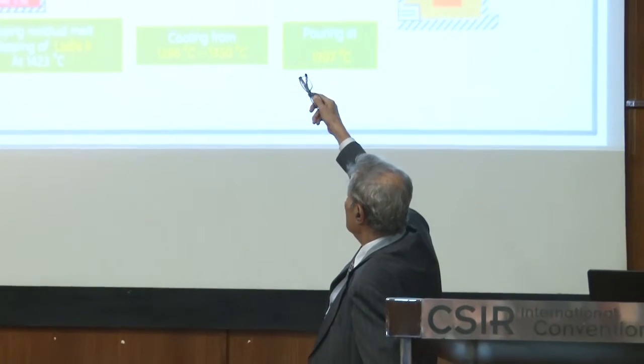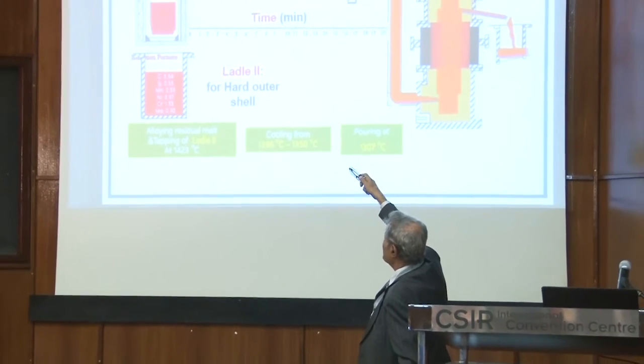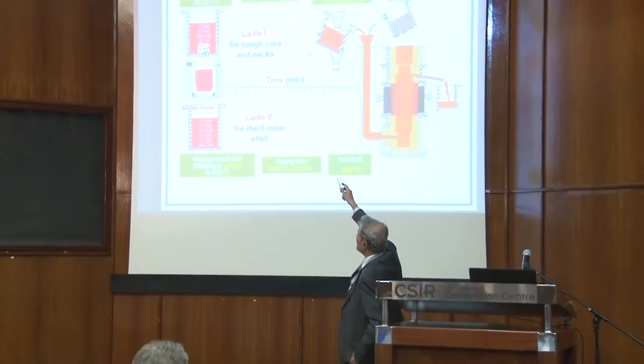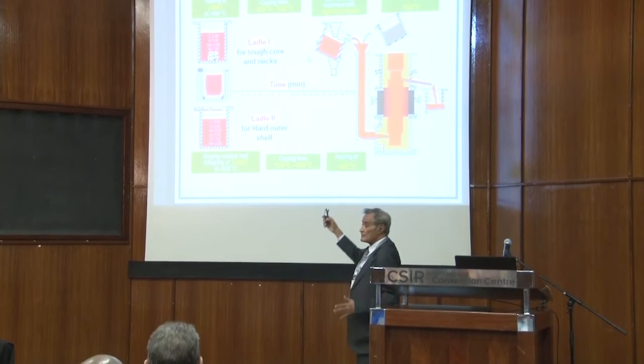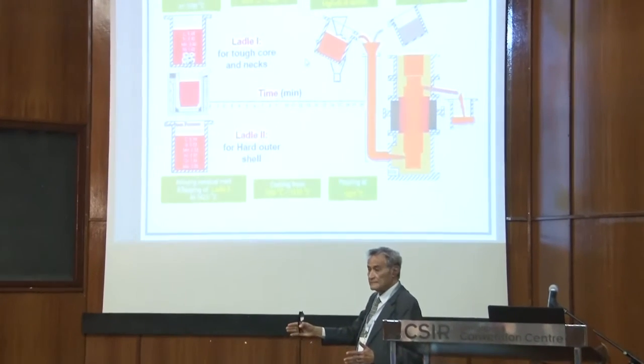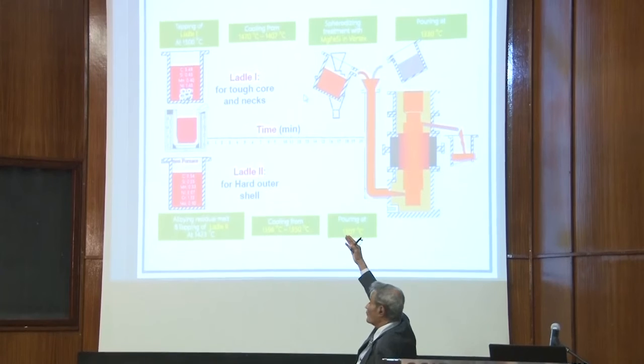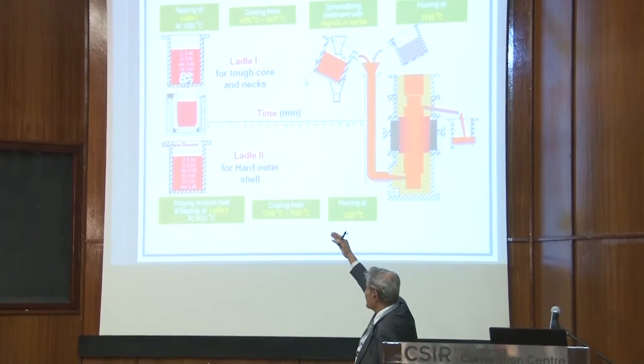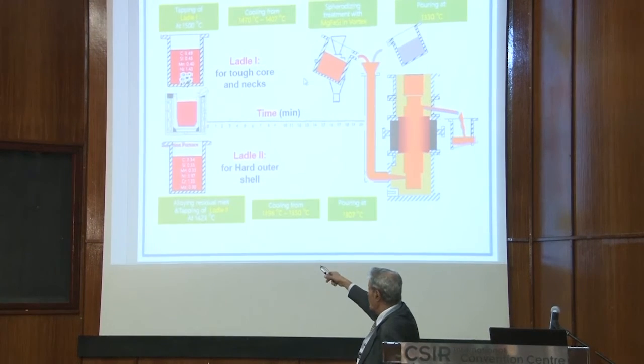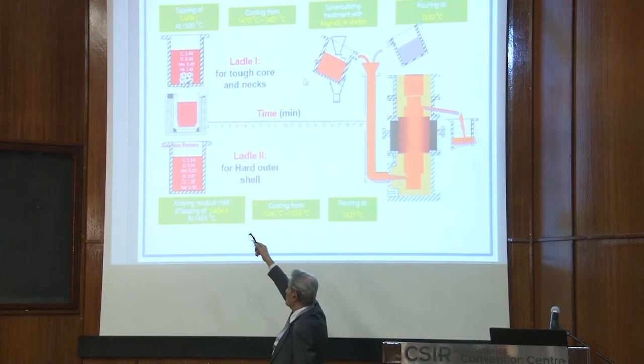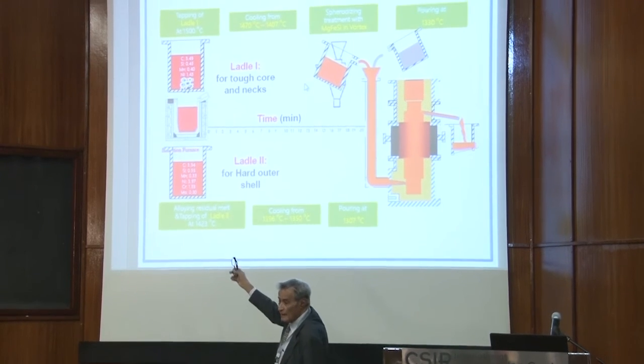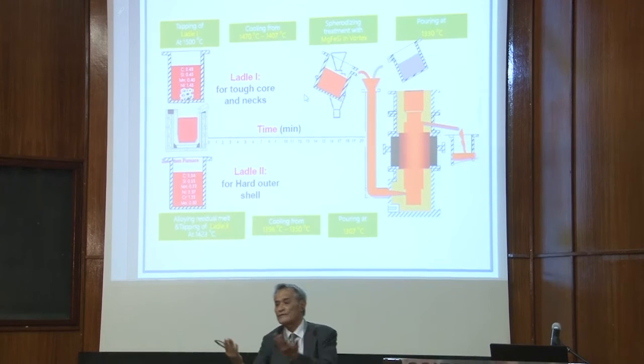This is how we just explain very quickly. This is the induction furnace in the middle, the melting furnace, and we have two ladles. First, we melt the low alloyed iron with, as you see here, chromium 0.3%, for example, nickel 1.4, and so on. This is the low alloyed iron, which is supposed to form the core of the roll. And we kept it away for a while. And then we added the rest of the alloying elements in the furnace, with the chromium up to 1.3, nickel up to about 4%. This is the high alloy, supposed to represent the outer shell of the roll.